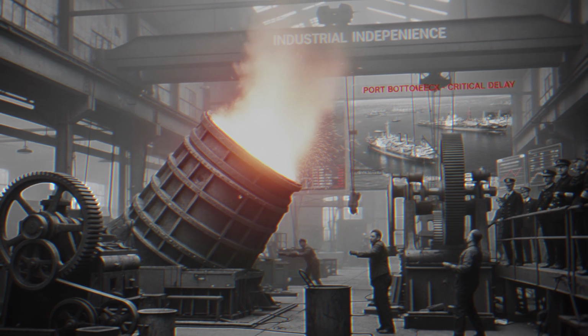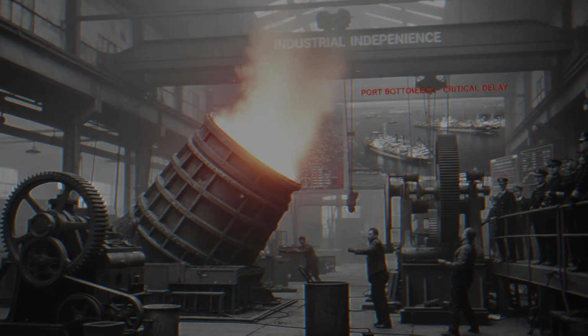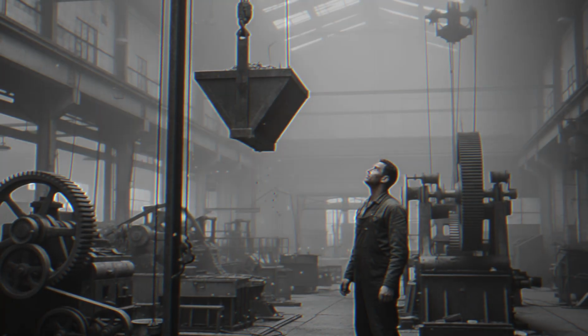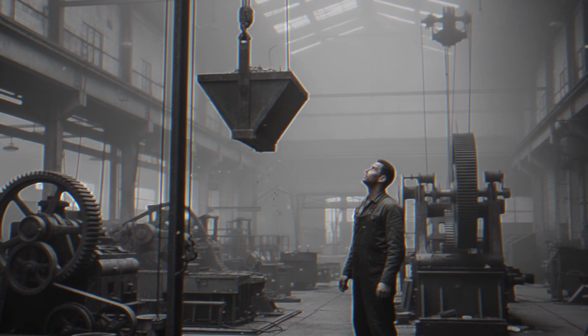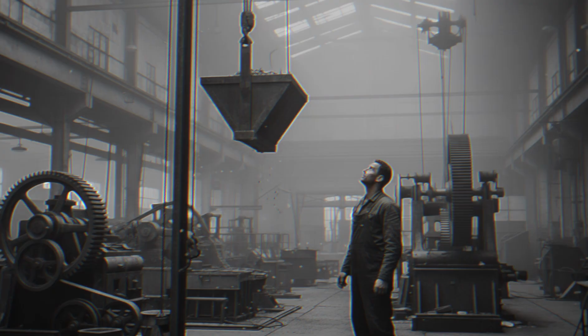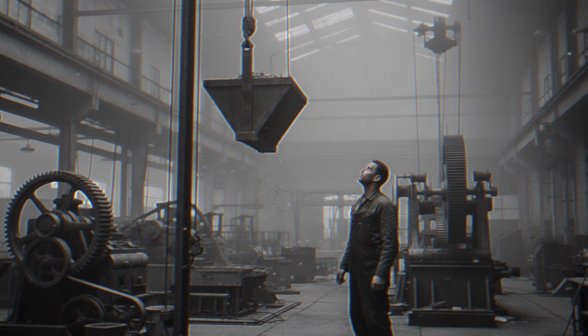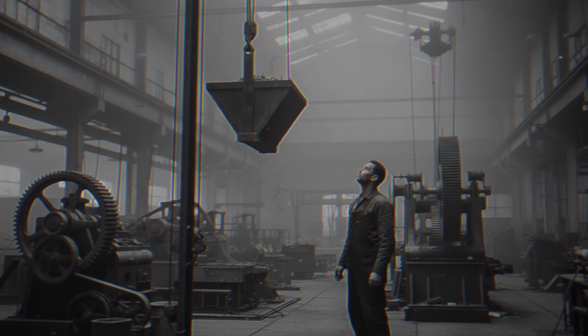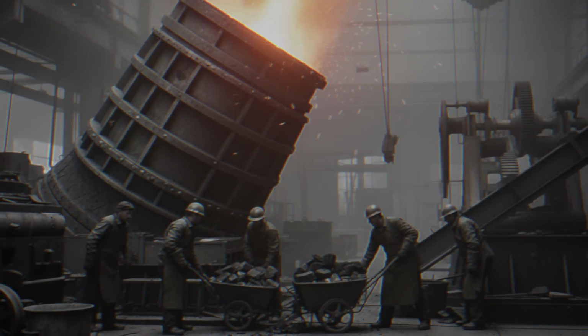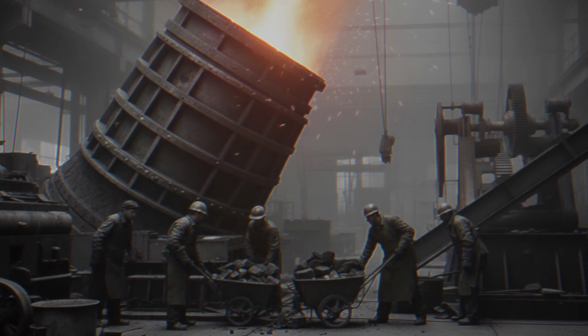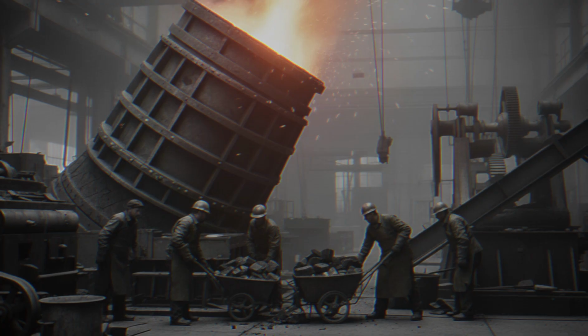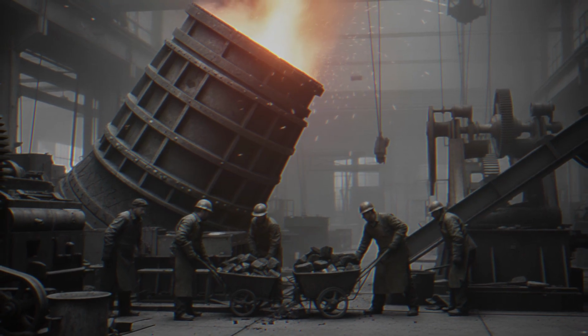Preheated air, called the hot blast, is injected into the furnace through tuyeres positioned near the base. The combustion of coke in the presence of this forced air generates carbon monoxide, which rises through the burden of ore and flux, and chemically strips the oxygen from the iron oxide molecules. What remains, reduced iron, sinks toward the base of the furnace due to density and temperature differential.